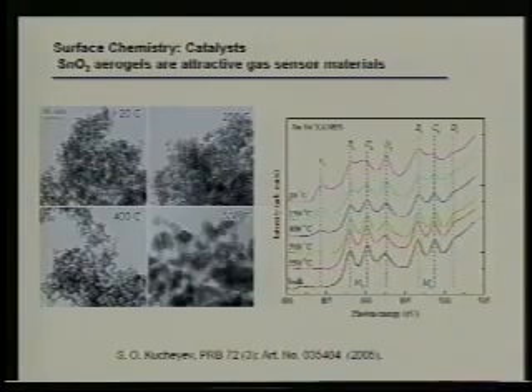And it's made as prepared, the 20-degree sample. And then we anneal it. There's your TEM pictures on the left-hand side, my left. And then you can see at 250, there's not that much change. At 400, you can sort of see the structure is beginning to change. And at 500, all the same length scales, there's a complete change in the size of the particle.